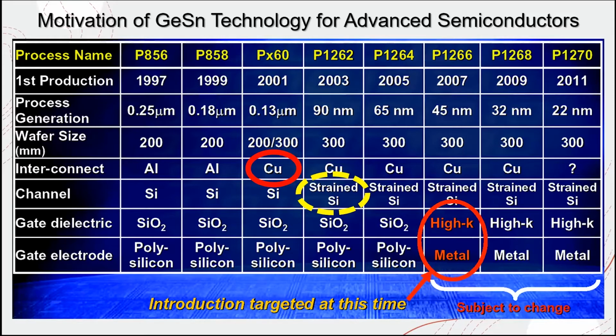Germanium has higher electron mobility than silicon and much higher hole mobility than silicon. When it comes to hole mobility, germanium has an invincibly high hole mobility compared with other well-known materials, including group 4 materials, silicon, silicon carbide, and other III-V compound materials. So what we can expect from germanium when it is incorporated into silicon can again be expected for tin in germanium. So if you incorporate tin atoms in a small portion into germanium, you can further increase the electron and hole mobilities.